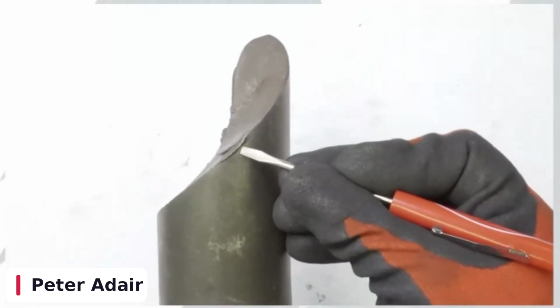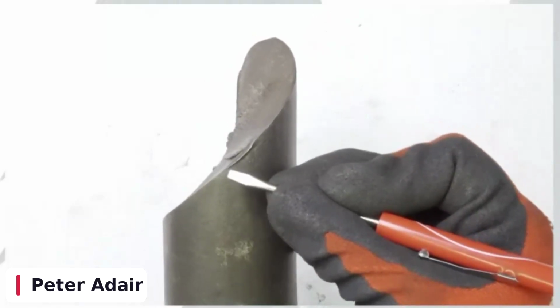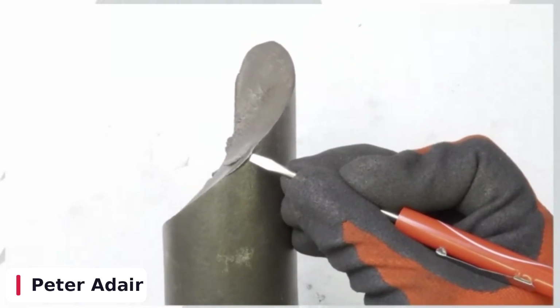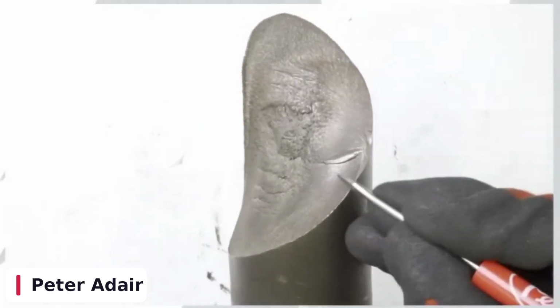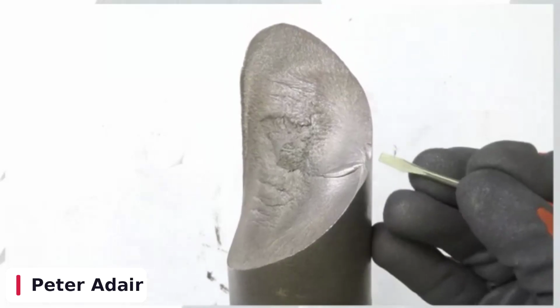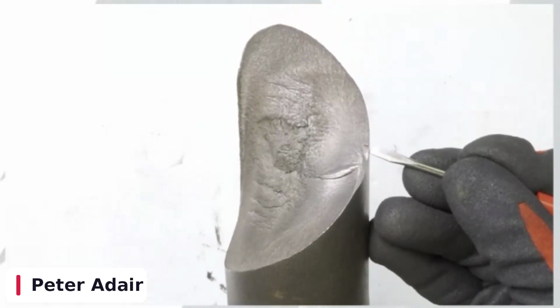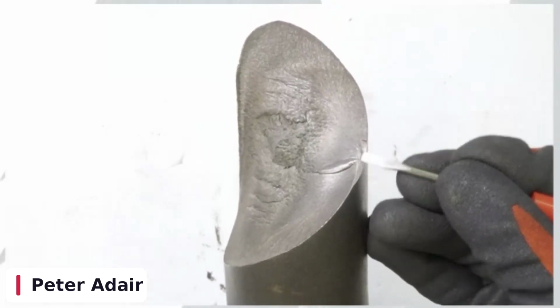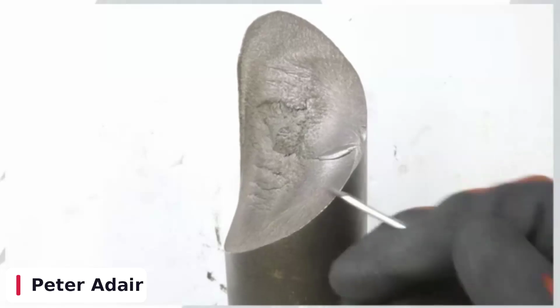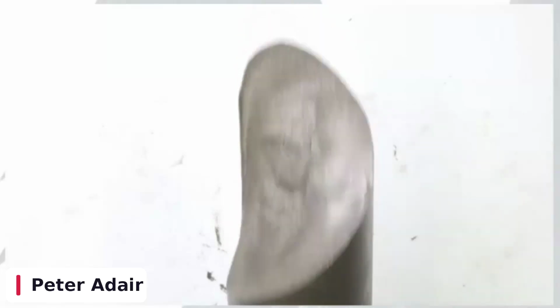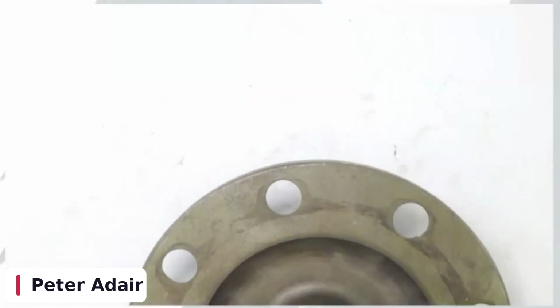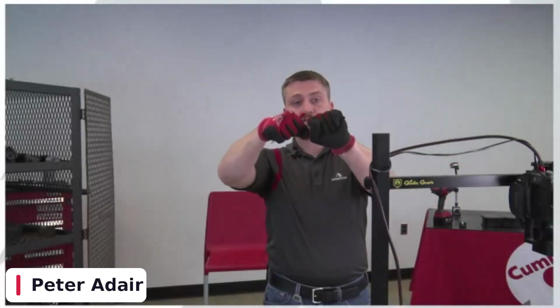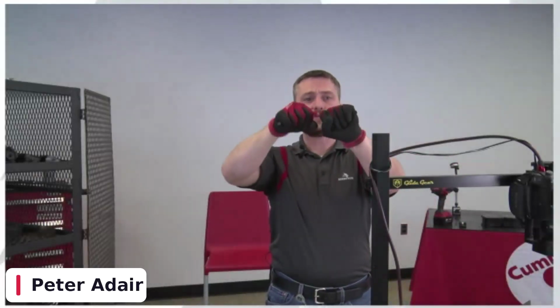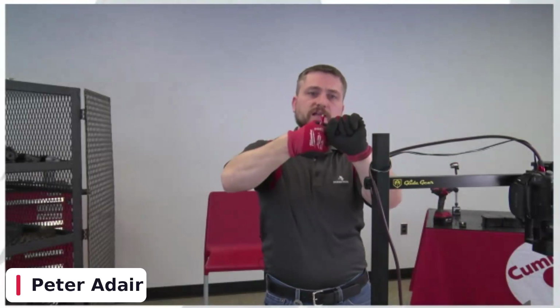So that one little dent, that one little stress riser is all it took for this shaft to snap in this location. So I have my origin, or my ratchet mark where it started. And then I have a small roll in the steel here where this was dented at some point in its life, which caused it to break here. So back to camera one. This shaft twisted up, loaded up, and it did that a few times. And then eventually when it loaded, it snapped all the way around and finished itself off.